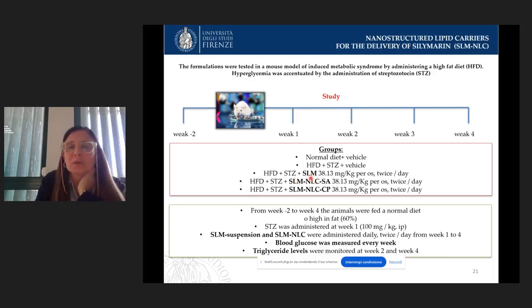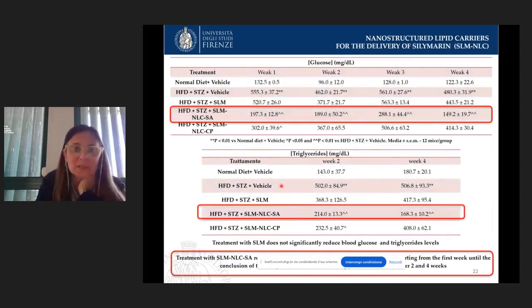In one group, NLC with stearic acid, another group, silimarin loaded in NLC with cetyl palmitate. We monitored during 1 month the blood glucose level and triglyceride levels. Here are some results. In particular, both formulations are active to reduce glucose and triglyceride levels, but the treatment with the NLC with stearic acid reduced the glucose levels and the triglyceride levels during all the time of the experiment. Then it maintained low levels of glucose and triglycerides for 1 month. And then the in vivo study showed the best performance of this formulation with respect to NLC made with cetyl palmitate.